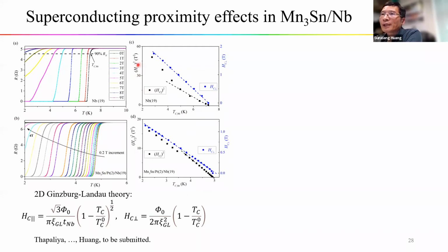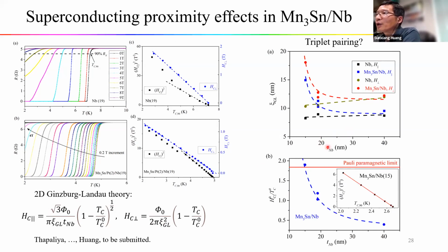For the in-plane field, the critical field squared scales linearly with the transition temperature, for temperatures above roughly 75% of the transition temperature at zero field. This feature can be well described by the two-dimensional Ginzburg-Landau theory, shown by these two equations. By getting the slope and the intercept of these dashed lines, we can get the critical field at zero temperature and the critical temperature at zero field, as well as the Ginzburg-Landau coherence length. So we plot those coherence lengths as a function of the niobium thickness.